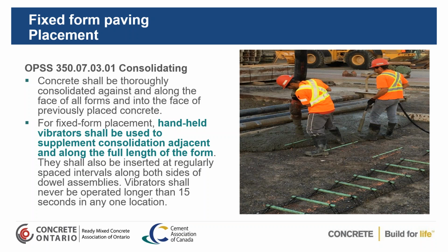So for looking at consolidation, we're looking at, again, OPSS 350 in section 70301. It gives you information on the consolidating of the concrete. Now, as I mentioned earlier, here they're using the roller screed, but they're giving additional consolidation. The concrete's being supplied by pump truck. This guy here is standing with the vibrating pencil vibrator, and what he's going to do is some additional consolidation of that concrete prior to the roller screed acting on it. Now, it is extremely important to use this device properly.